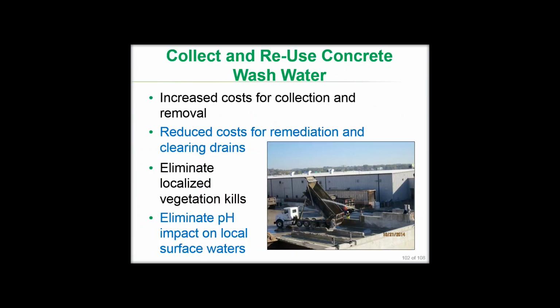We're seeing a lot more use of wash water, concrete wash water collection and reuse of that wash water. This is a picture of a site down in Tennessee where we're doing that, and this reduces a lot of the problems with remediation and clearing drains when you're not doing this sort of thing. Eliminates the potential for localized vegetation kills when you're out washing the field and you're not confining it to a storage pit, and eliminates the potential for pH impact on local surface waters.